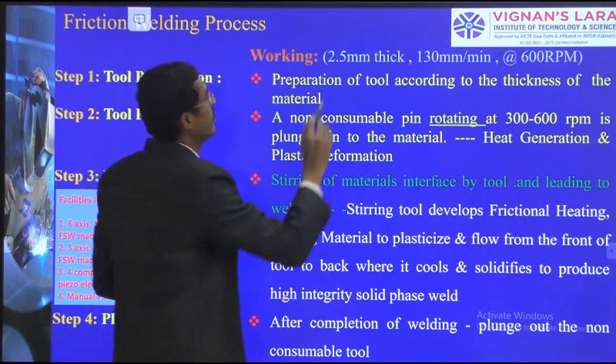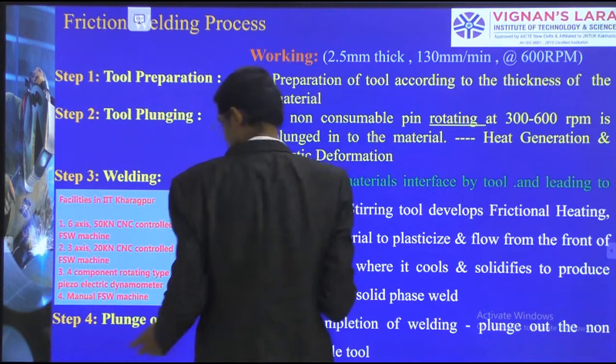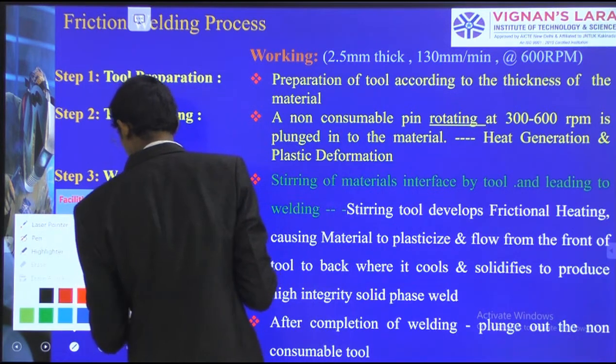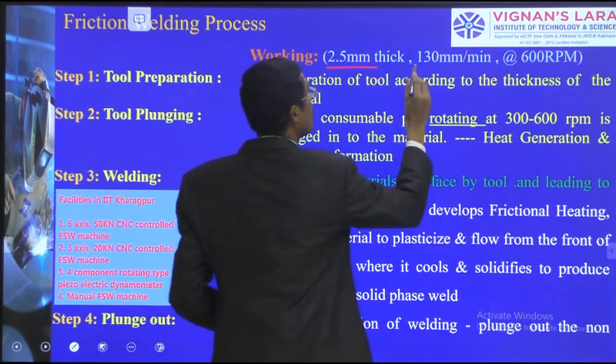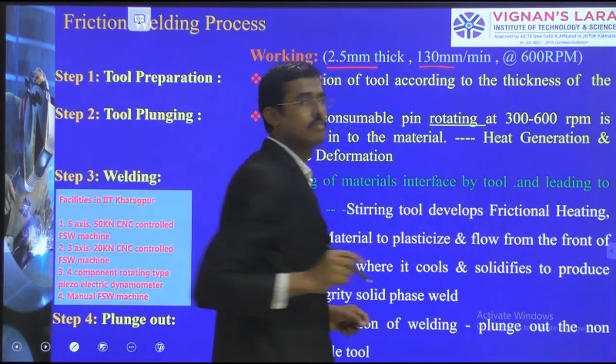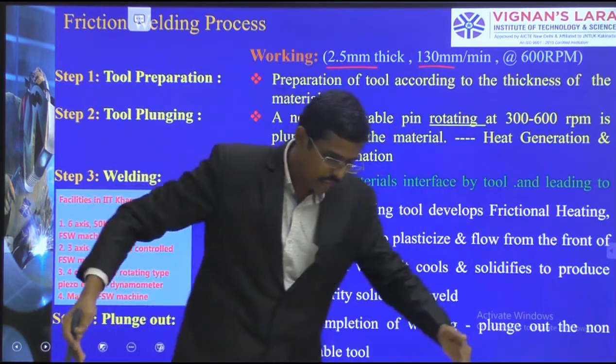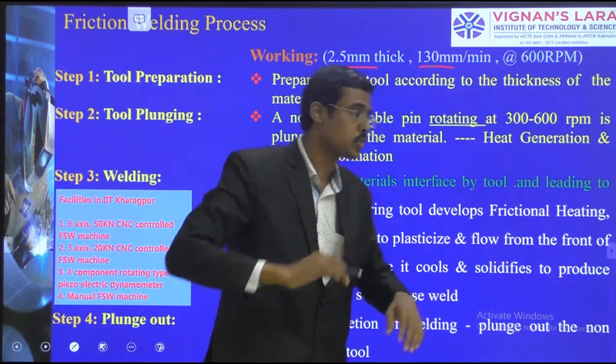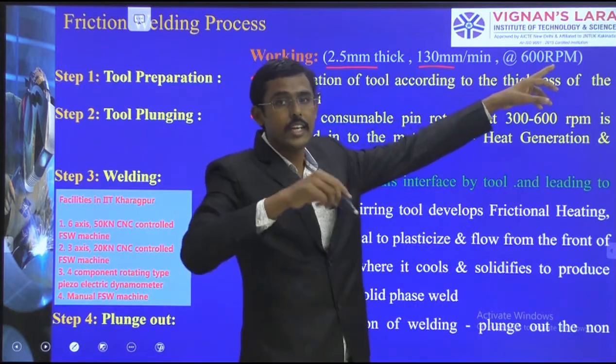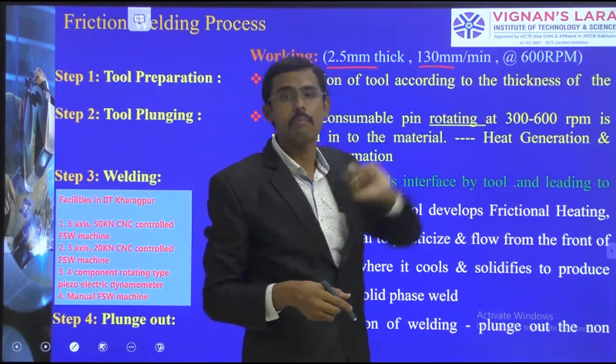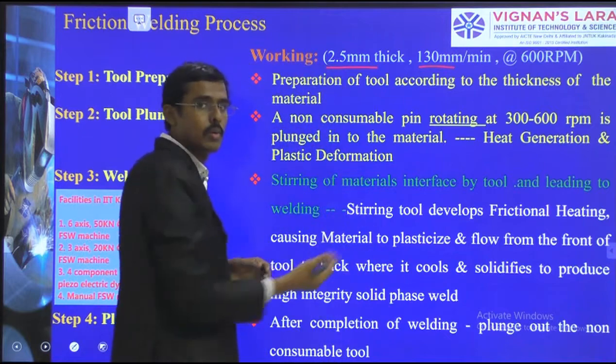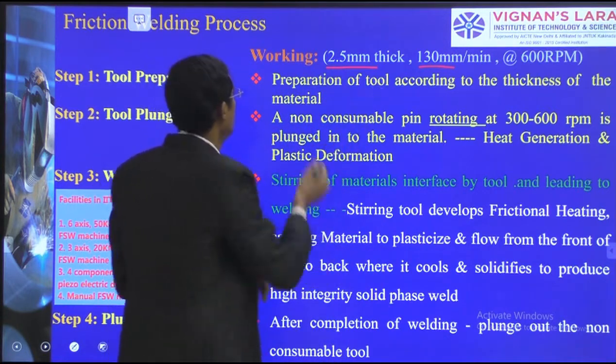For working, we have taken a 2.5 mm thickness plate, and then 130 mm per minute speed. I am moving at a total length of 130 mm per minute welding speed, and at a tool rotating speed of 600 rpm. In such cases, we are able to do it. It is a common range.